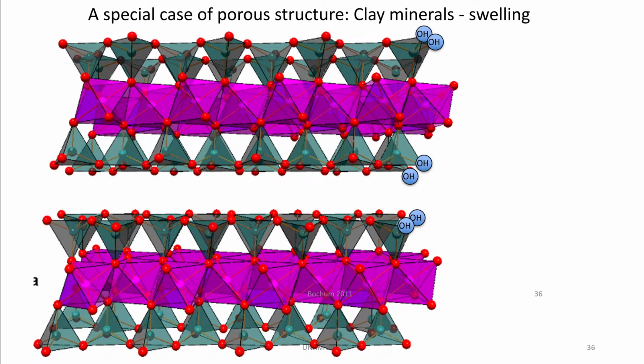So one source of variability is in the atomic composition, but something very interesting is also the type of porosity. Between two successive layers, between two flat layers that expand for maybe several microns, you have the interlayer space here, and it can be expanded. If you have a large molecule and you have some kind of driving force to make it come inside the clay layers, well, it can increase the spacing. It's tunable porosity, if you wish. So that's yet a different type of porous structure.